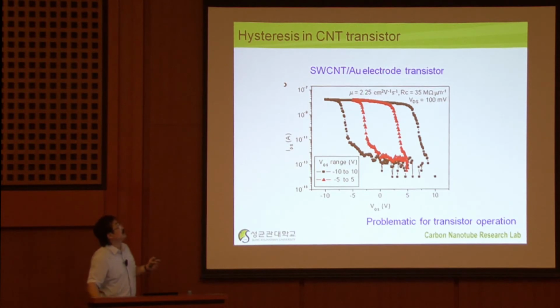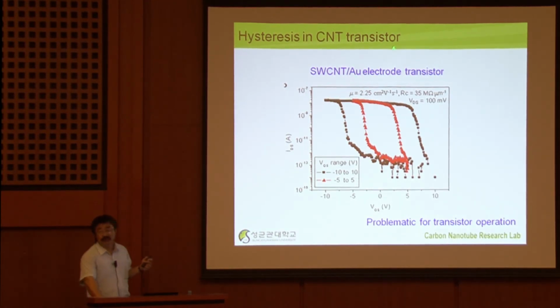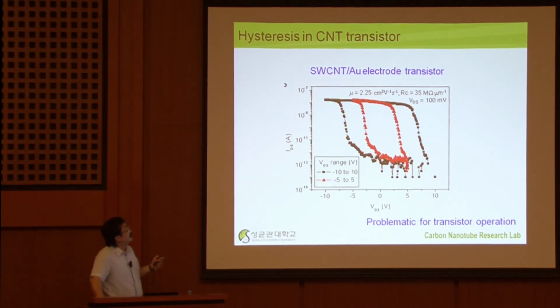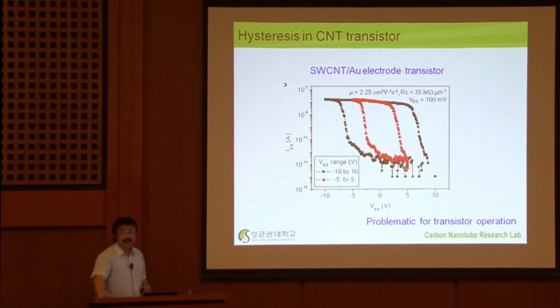okay, one serious drawback of using a conventional metal electrode is this one. So we have this gold electrode. Gold is typically used. But look at this one. You have this gate voltage sweeping, 5 volt, and then you increase this gate voltage sweeping, and there is large hysteresis. This is actually a serious drawback in terms of device operation. And we cannot avoid this using this typical metal electrode.